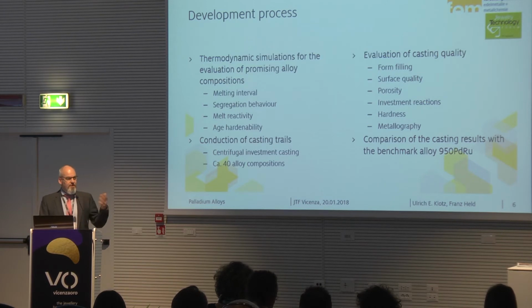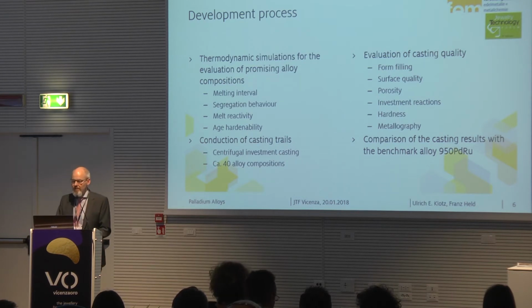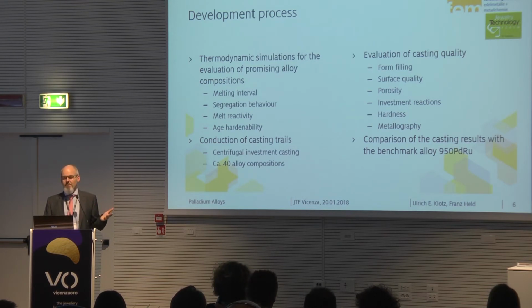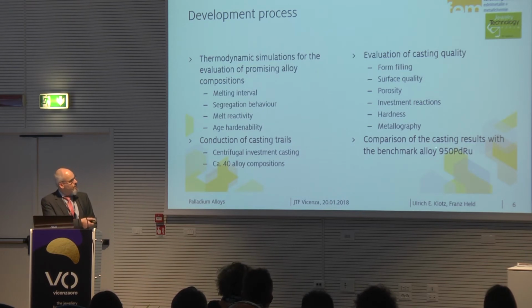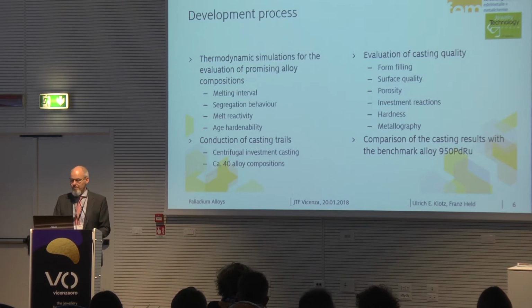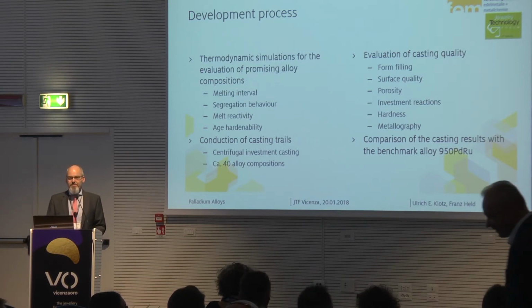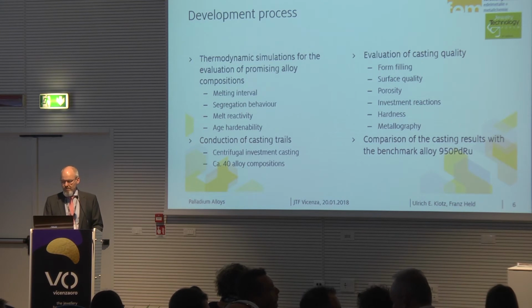Then we started working. We developed about 40 alloy compositions, tested them, made centrifugal castings and evaluated the most important parameters like the form filling, the surface quality, the porosity, of course, and the hardness, which was one of the key points. Our benchmark was always the most established alloy, which is 950 palladium ruthenium. Well, but if this alloy is established, why do something new?